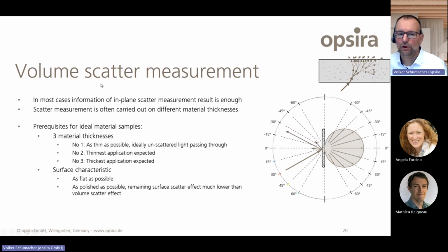And I also wanted to talk a little bit about volume scatter measurement. In most cases, the information of in-plane scatter measurement data is enough. That means we need only one cut in transmission and one cut in reflection. But here we are measuring normally on different material thicknesses. Normally 3 thicknesses are best, ideally.